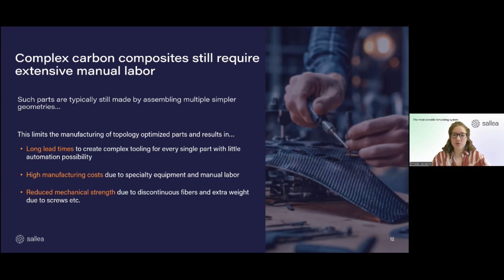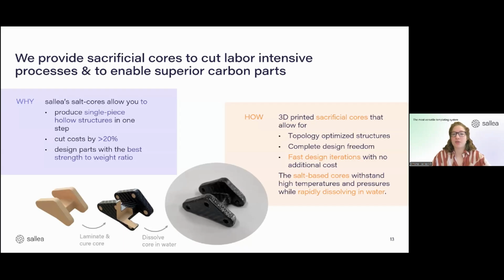And one of the solutions to circumvent that are sacrificial cores. Now, why are we using sacrificial cores? We see a huge benefit because single piece hollow structures can be manufactured in basically one step, two steps. And this is a great benefit. This allows us to cut the costs by more than 20%. And it also allows you to design the part with the best strength to weight ratio, so that you basically only have the material where you actually need it.